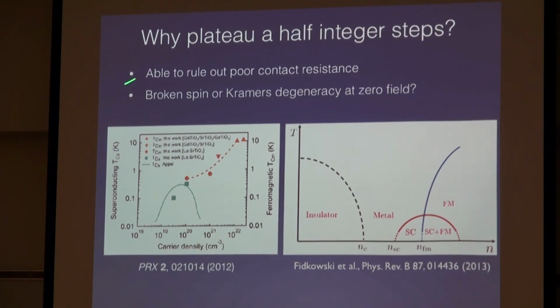Well, one is that you have poor contact resistance. We are able to rule this out for two reasons. One is that we've seen this behavior over many devices when we see the quantum-point-contact-like behavior, and it would be rare that they all seem to have the same contact resistance. What we've done in the superconducting regime is actually probe that contact resistance, how well coupled the system is at that interface, and they're actually very well coupled. And so we've been able to rule out contact resistance as a source for these half plateaus.